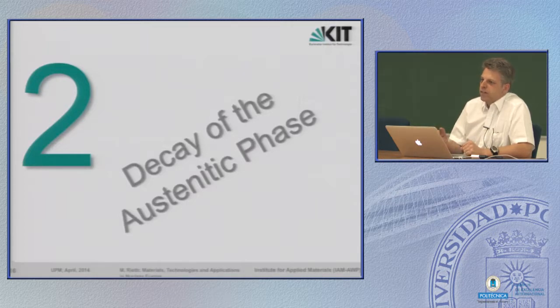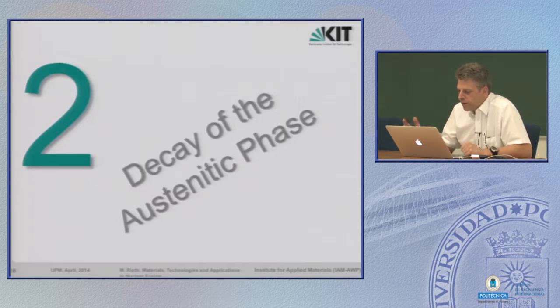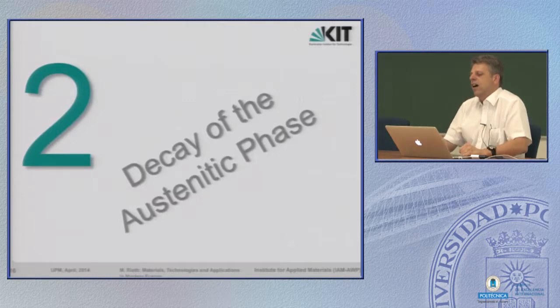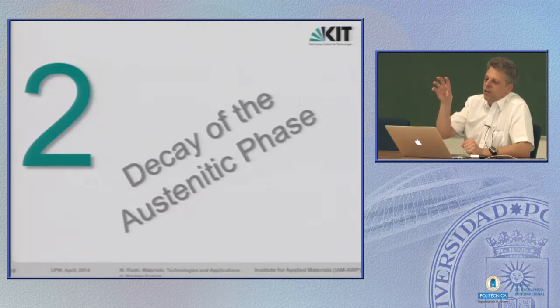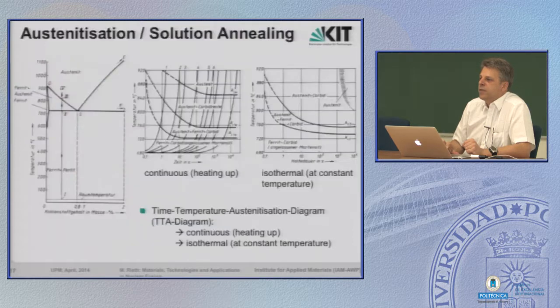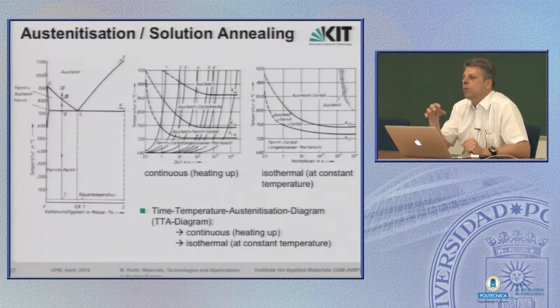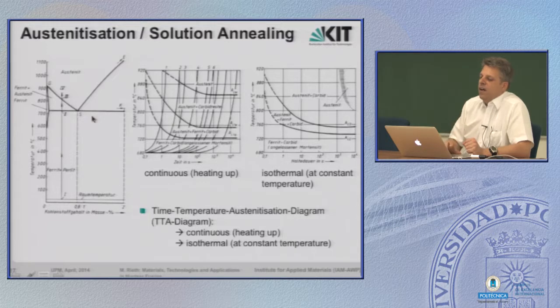Now, the most interesting part in steels doesn't end here. It is very tricky, or beautifully unique, I think unique to iron. If you heat it up into the austenitic phase and then you cool it down with varying speed, or varying quenching rate, then something strange happens, because then you leave the phase of thermodynamic equilibrium. Time scales are much faster, and as a consequence, the phase diagrams are not valid anymore. They have to be modified.